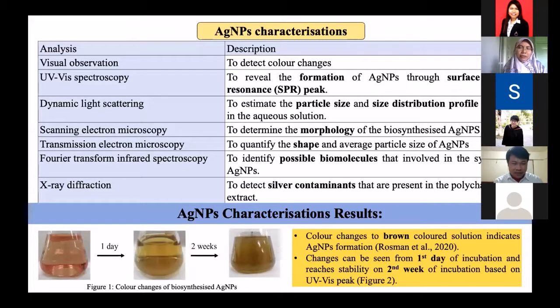So how do we characterize the silver nanoparticle synthesis? As I mentioned to you, we use visual observation to detect color changes. We use UV-visible spectroscopy to measure the formation of the silver nanoparticle peak using the surface plasmon resonance peak. We also use DLS to see the particle size and particle distribution, and then we confirm the morphology of the silver nanoparticle using SEM and also TEM to know the exact size of the nanoparticle.